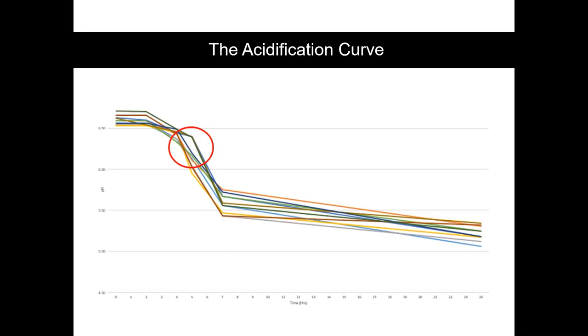And if we're coming into pH 6.3 too quickly, well, we need to take some corrective actions. Maybe we need to reduce the starter culture in the next day's dose, or cut the curds finer, or possibly we need to scald the curd to a slightly higher temperature to drive out more moisture. Or maybe we need to do a little bit more curd washing in order to reduce the total acidification. But pH 6.3 or above, at the point the curds are pre-pressed and then go onto the cheese presses, is the essential process control that will ensure quality in our final cheese.